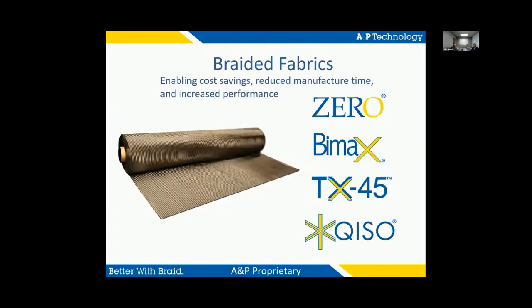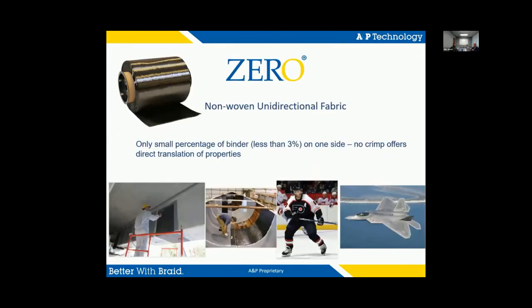Braided fabrics. It's neat that this is actually the only product that's not braided, but what we're able to do is to get a very wide and very high fiber areal weight unidirectional material in a sort of columnized form or a fabric form that can then be readily infused. So think 800 plus GSM, but still able to infuse quite readily.